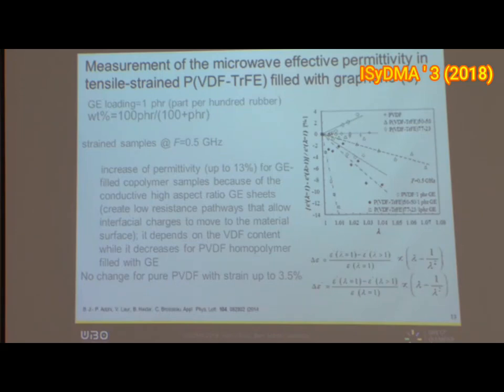So very interesting results, which means that you can control simultaneously the dielectric and the mechanical properties of this sample, which is a very interesting result for actuation applications.